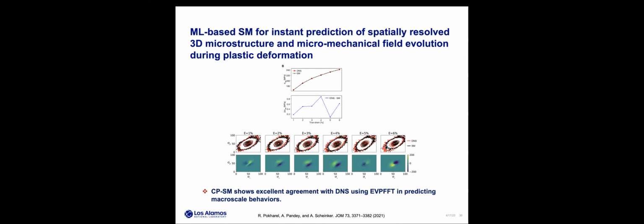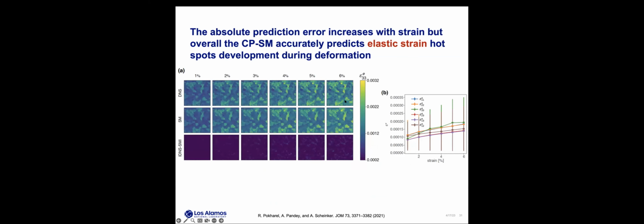So here I'm just showing the comparison between the EVP-FFT simulation and the surrogate model predictions of the average von Mises stress evolution with strain, and also the 2D bin histogram of the principal stresses to look at the yield surface evolution from the EVP-FFT and the surrogate model. And this shows that the model is able to reasonably predict this macroscopic material response just based on the microscale training data that we provided it. So in the next few slides, I'll show you the spatially resolved strain and stress fields comparison between the surrogate model and the EVP-FFT simulations.